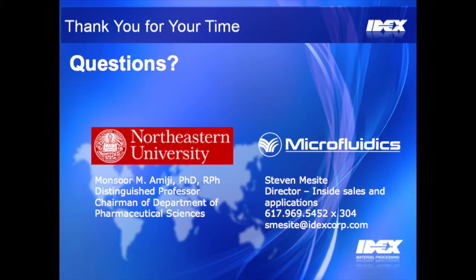So the good thing about nanoemulsion, and I think part of the whole issue with preparing nano formulations of drugs, is that they are sterile filterable. You can filter them using 0.22 micron. Because the size, as I mentioned with our DALDA nanoemulsion, was around 100 nanometers. Same thing is true for the cyclosporine nanoemulsion. The size of the droplets is around 100 nanometers. So they're easily sterile filtered through 0.22 micron, and that allows us to create a sterile formulation at the end.